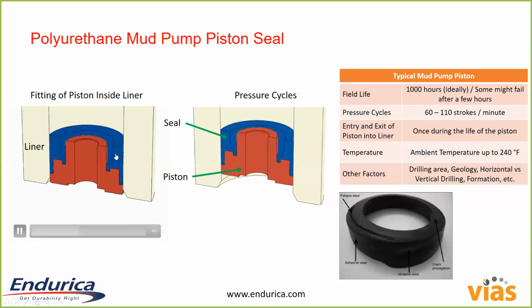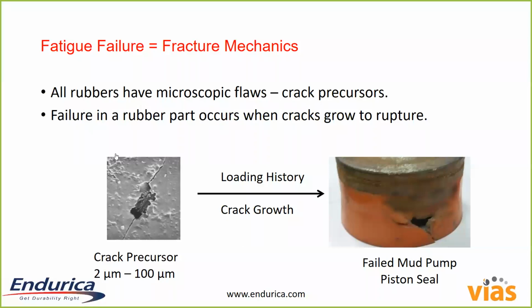The basis for our analysis is the assumption that whenever you have rubber, if you get out a microscope, it is filled with microstructure, right? There are crack precursors already in that. Now, granted, they may be very small. Typically, they would range anywhere from maybe 2 microns up to 100 microns. But failure analysis is all about figuring out where and when those small crack precursors grow up to a size where they become a problem.